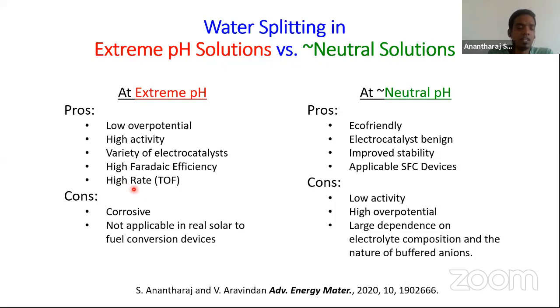But the cons are these extreme pH solutions are highly corrosive, which means that we will be running out of electrode materials after some time of operation. So we need to keep on changing the electrode material after a particular period of operation, which is not advisable when the electrode material is huge in terms of expense. The cost of the material is huge. If you need to replace the material every once in a while, it is again going to increase the cost of production of hydrogen. So all the pros that you get with extreme pH are going to be affected by this factor.